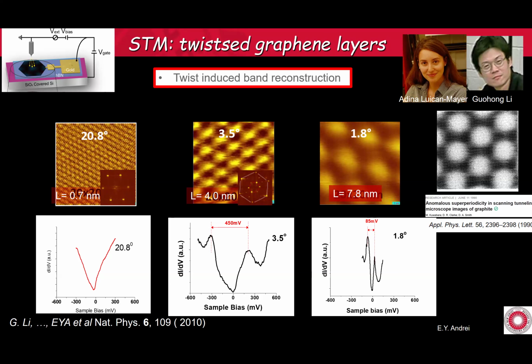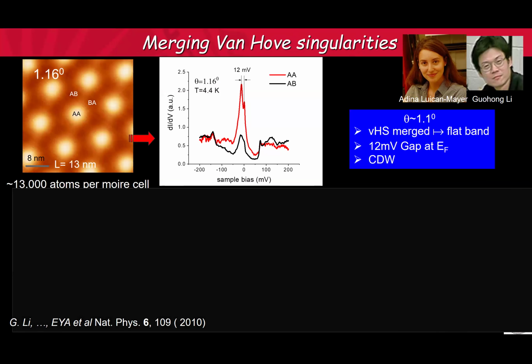But what came as a huge surprise was that not only does it make pretty patterns, but it also reconstructs the band structure. So at a large twist angle, we get van Hove singularities whose separation is kind of linear in the twist angle. And as you decrease the twist angle, they come closer and closer. By the time you get to what we now call the magic angle, they merge and you get one flat band. At the Fermi level, you have a little gap, which coincided with the charge density wave that we saw in topography and in density of states maps.